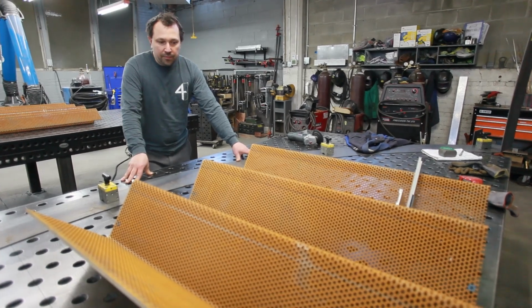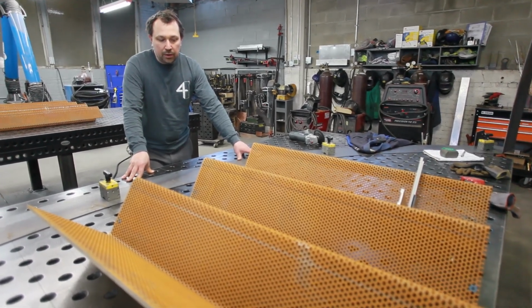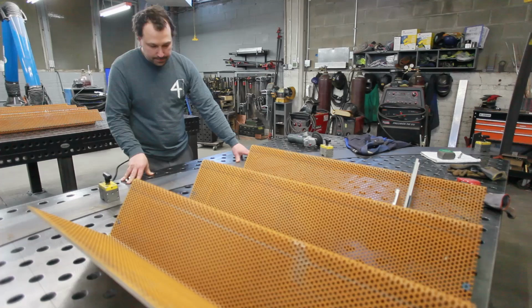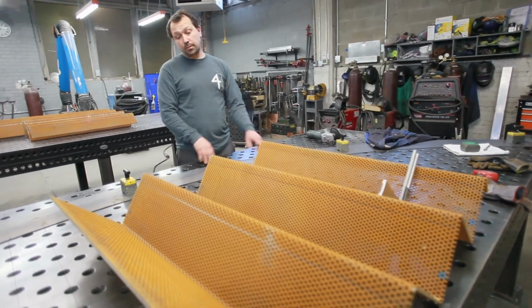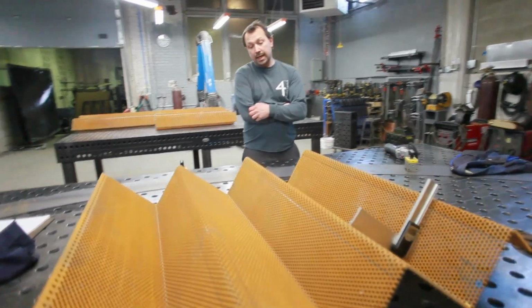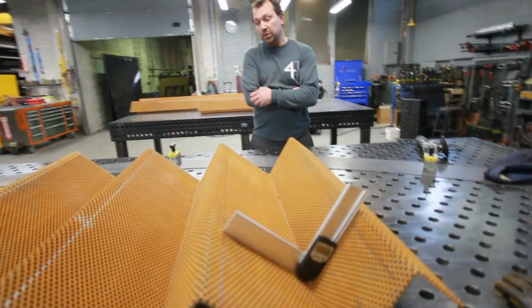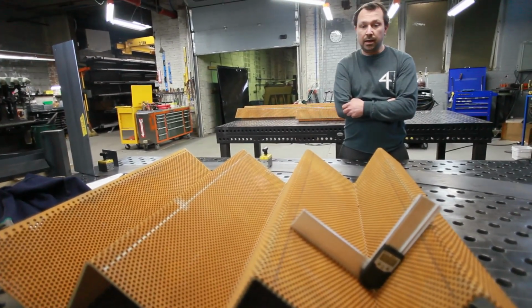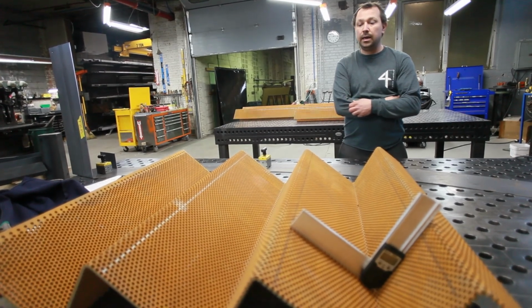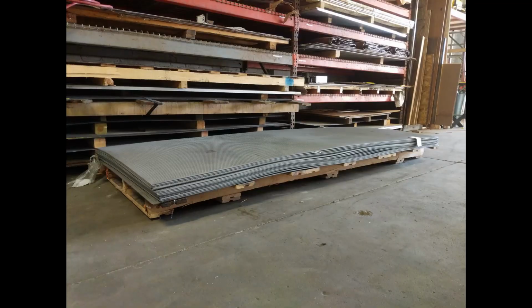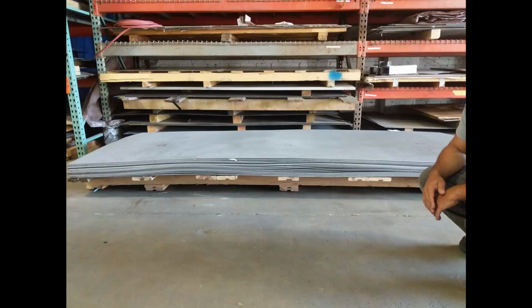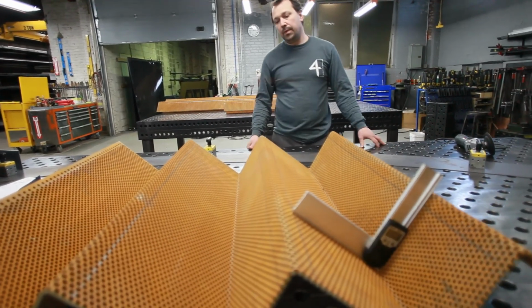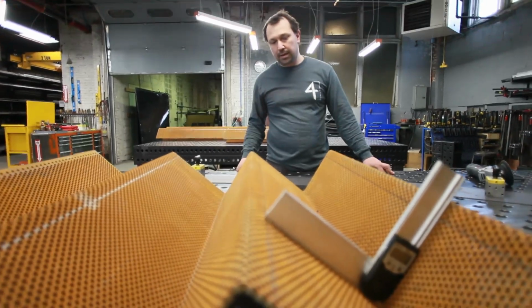Which led us down the road of figuring out how we could make the material without bending it, without breaking it. So we sent all of the McNichols material to an annealer. Before it could be annealed, they wanted it to be sandblasted. When it came back from the annealer, the material was very unflat, which was a problem during bending. But once the material was bent, that flatness was no longer an issue.